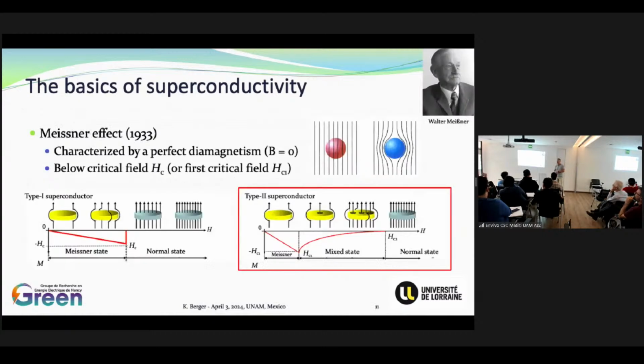The second effect, which is maybe not well known, is what we call the Meissner effect. So this is also a very special state of the superconductor. It was discovered by Meissner. In this state, when the superconductor is cooled down, there is an expulsion of the magnetic field. So this expulsion does not appear with any variation of the field. So this is not an induced current, for example. This is a completely different magnetic state that makes the magnetic field completely expelled from the superconductor.